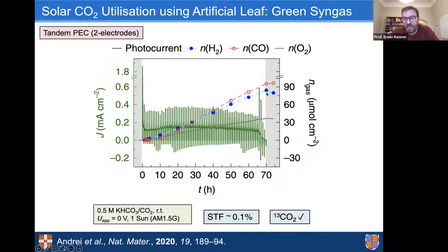What you can see here in the color traces, in the red, blue, and gray, are the amounts of products we are forming. So red is the carbon monoxide, blue is hydrogen, and the gray trace is oxygen. So it's good, steady activity, but you can see that the ratio is not perfectly 2-to-1 in terms of syngas to oxygen. There's not enough oxygen in the system. And the reason is because the Faraday yield for water oxidation is not quantitative, for reasons I can also explain later, but that's not unexpected. And overall, at least for a very first system, we were quite pleased with that.